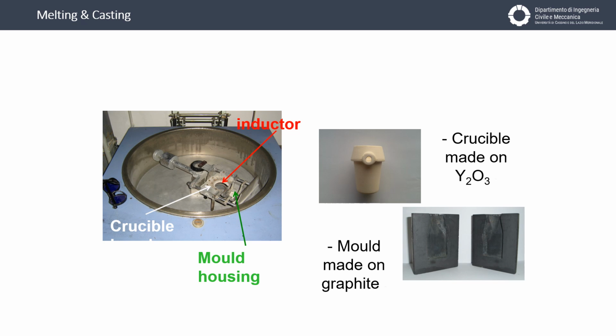has been to produce the material using a vacuum crucible posed in a furnace without air, and using a noble gas like argon in order to eliminate oxygen inside. We use the crucible made of yttria because the yttria is very stable in terms of chemical action, and the casting has been in a mold made of graphite, as you can see in the slide.